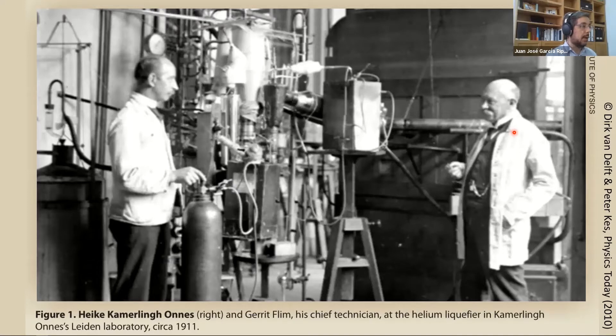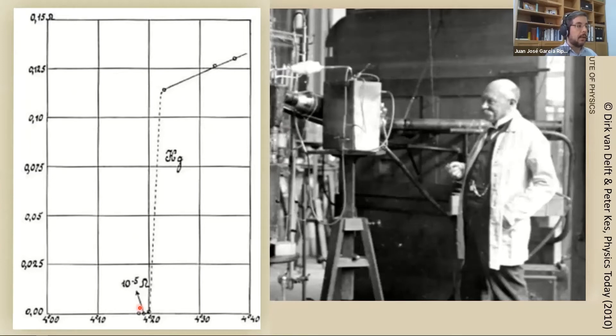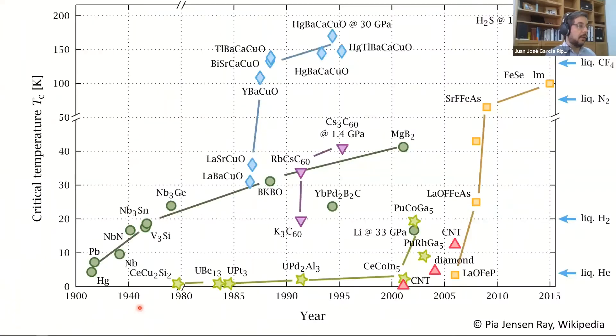Onnes decided to put materials into his fridge and observe how they reacted to low temperatures. He discovered that mercury, at a given point, transitioned from being a conductor with some resistance to a material exhibiting no resistance at all — a superconducting transition visible in his original notebook. This discovery seeded a field that revolutionized condensed matter physics. Since then many superconducting materials have been found: elemental metals like lead, mercury, aluminum, and niobium, through to ceramic high-temperature superconductors.